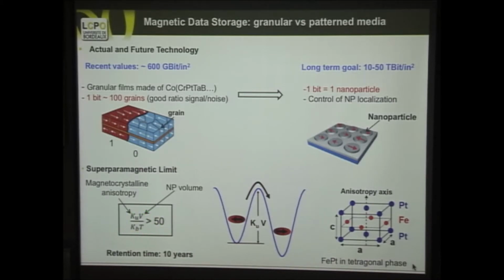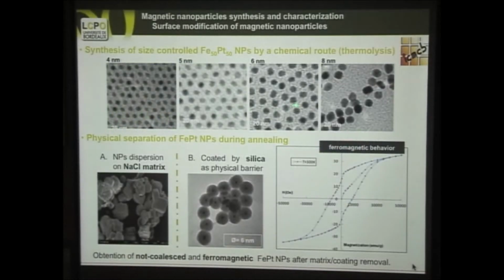If this factor is bigger than 50, then it will not switch. Actually, if you have your disk, you don't want all the information in there to disappear in one evening. This parameter here is what makes it stable. So we found in the literature, and we have a very good laboratory, ICMCB in Bordeaux, that they have produced these platinum-iron crystals, and you see here the different sizes of these crystals. But once you have them, then you have to magnetize them.